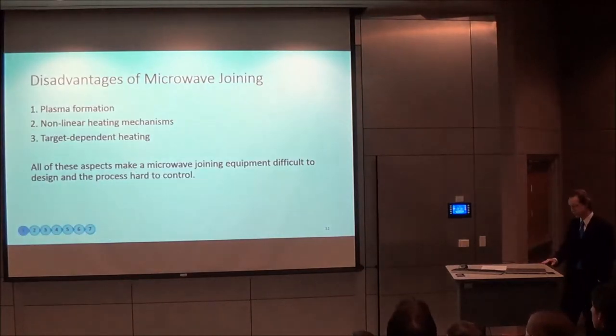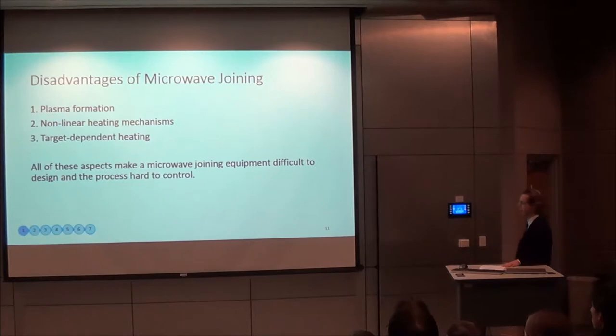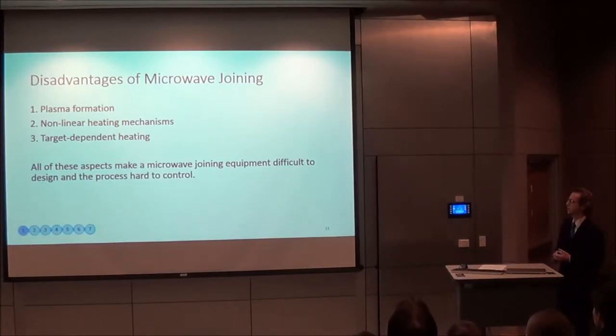But there are several disadvantages to using microwave joining. For one, the formation of plasma is difficult to avoid unless you remove every molecule of air from the medium. In addition, the heating mechanism is very nonlinear, and the material properties that govern it change significantly with temperature. For example, the hysteresis effect only operates up until the Curie temperature of the particular material is reached, and then you don't have that heating mechanism operating anymore.